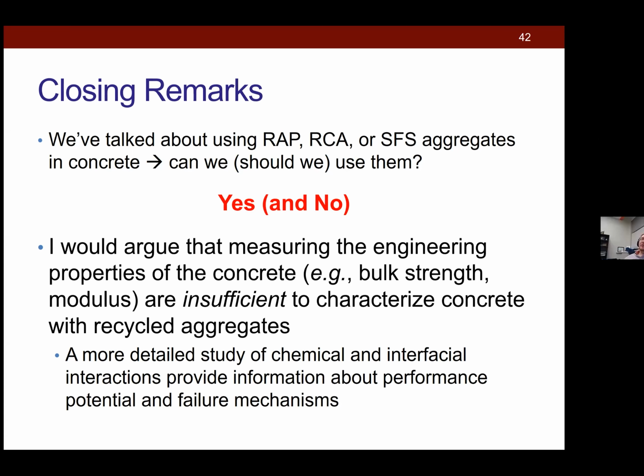Yeah, I would say you still should batch your water appropriately, assuming you have, let's say, a normal moisture absorption capacity. I mean, if we're looking at a granite that has 0.5% moisture absorption, it's probably not going to make a whole lot of difference if you adjust the water there or not. But when you're getting into these ones that want to absorb a lot of moisture, that's when you're running into issues. So in the case of roller compacted, are you mixing everything in dry?